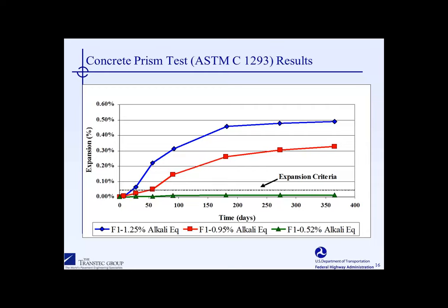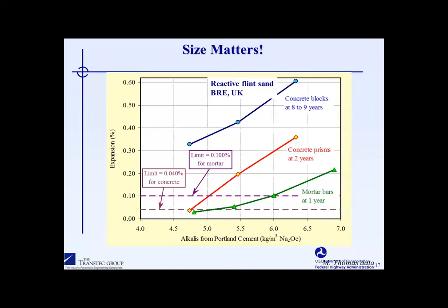But what's most important, and the point of showing this graph, is that the lowest alkali mix at 0.52% showed essentially no expansion for the entire one-year duration, and this is entirely due to the fact that leaching occurred in all of these prisms, actually. But for this particular mix, the leaching was such that it dropped the alkali content of the mix below the limit at which it would actually expand in the field. So this just highlights the point that one cannot use this test for establishing an alkali threshold. The next slide shows similar data from a different study performed by Mike Thomas.